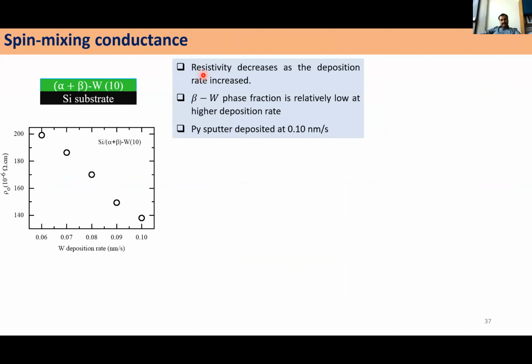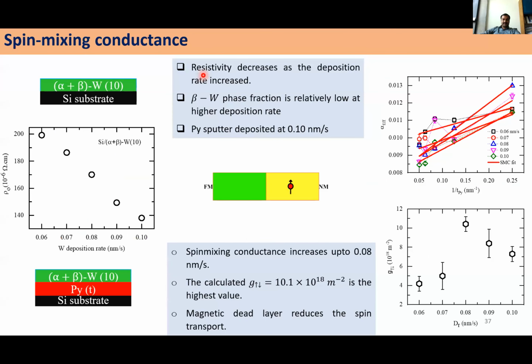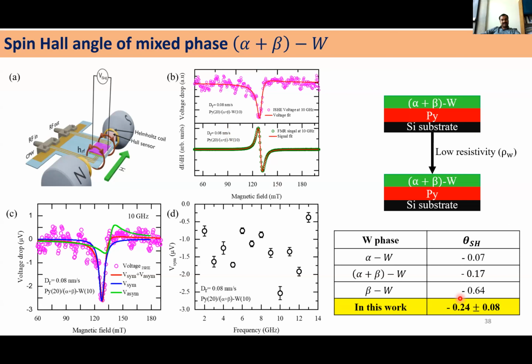Right? So we have used a similar spin mixing conductance method, that is the spin pumping from a ferromagnetic layer, and we have again used nickel iron as our ferromagnetic layer. And we found that the spin mixing conductance at the interface is 10.1 × 10¹⁸ per meter square. And using the inverse spin Hall effect, we have found the spin Hall angle. So basically, by tuning the deposition rate, we could get a low resistive mixed phase. In this low resistive mixed phase, the spin Hall angle of tungsten is found to be around 0.24. As compared to the literature, it is higher, that is 0.17, and we found it to be 0.24.